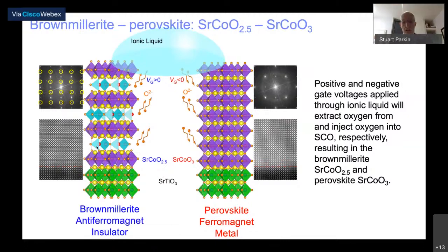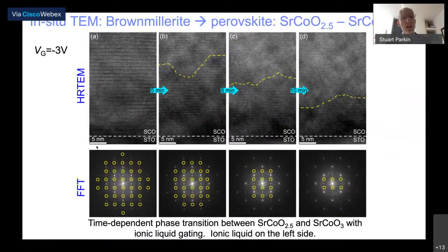We published this two years ago in Nature Communications. On the left-hand side, you see a high-resolution transmission electron micrograph of a brownmillerite. I hope you can see the unit cell is doubled because of the oxygen removal. But as we start to liquid gate the system, you can see in B from the surface, it's converted to the perovskite. And then as you wait, it takes a few minutes, we can convert the structure here, which is 100 nanometers thick, from the brownmillerite to the perovskite. This is reflected in the fast Fourier transforms at the bottom. The larger unit cell in the case of the brownmillerite is converted to a smaller unit cell of the cubic system, the perovskite, during gating.